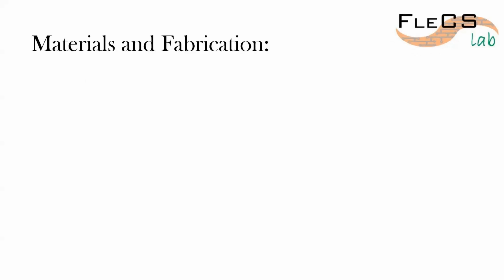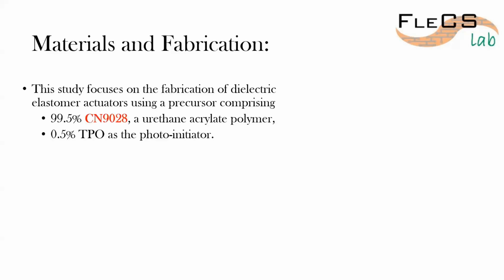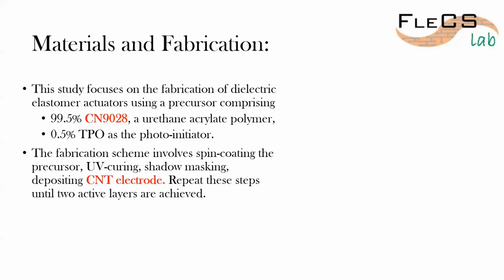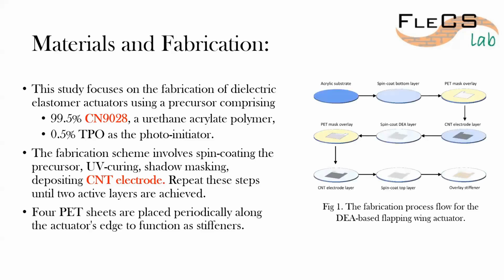So the way we went about it is that we fabricated these using a urethane polymer with a photo initiator, and they're spin coated and then UV cured to get the thin film. And on that, we put a CNT electrode thin film, which is masked using a PET shadow mask, and that PET shadow mask is made using laser cutting. And we typically have to repeat this process for at least 2 layers. In this case, we're making a top flapper. So for the top 2 electrodes, we had to repeat this process twice.